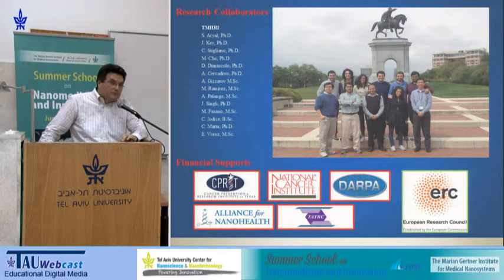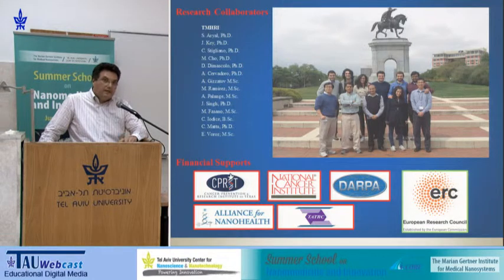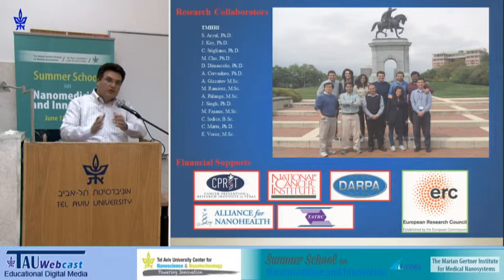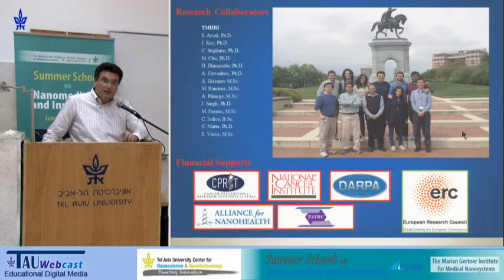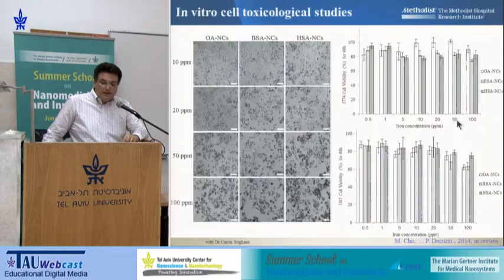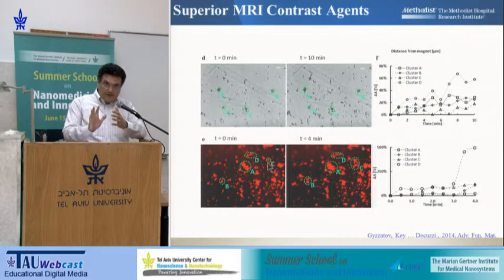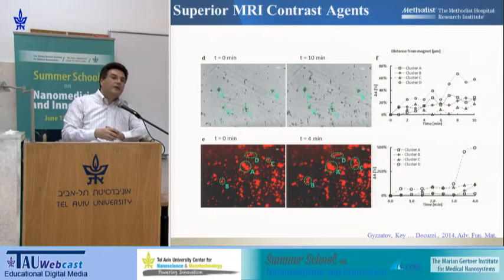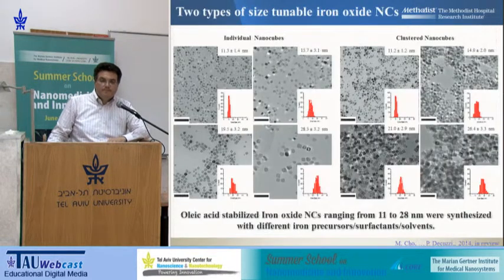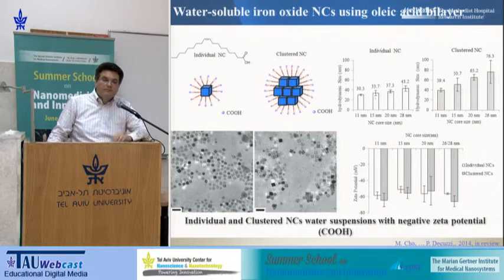Did you observe the formation of clusters of aggregated particles? No, and we don't see that, not even with the nanocubes inside, because the nanocubes are 20 nanometers in size, so they are still superparamagnetic, and they will become magnetic, which will foster the agglomeration, only in the presence of an external magnetic field. And that's actually one thing that we are using. If I may, this slide that I couldn't comment on shows that if you apply a magnetic field, these particles work as a local magnetic dipole that attracts other particles passing nearby. We have seen that also in vivo. But if they're not exposed to a magnetic field, they are not magnetic.